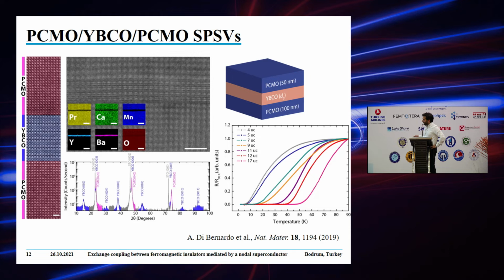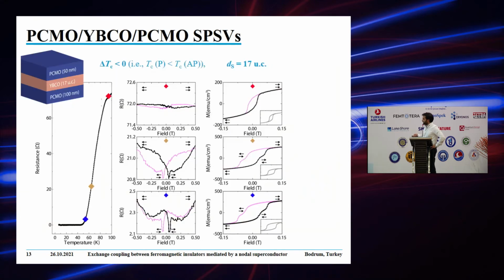Now, as you decrease the thickness of the spacer, you can see that there is a broadening of the transition, and that was also reported in the literature. But these oxide pseudospin valves show very sharp interfaces, so there is no mixing between the layers. So then, as I said, we started to do these magnetoresistance measurements, and we started from the structure with 17 unit cells. So 17 means thick YBCO.